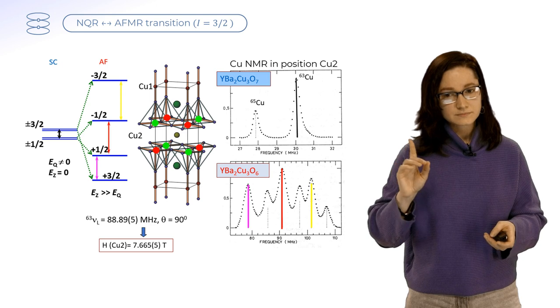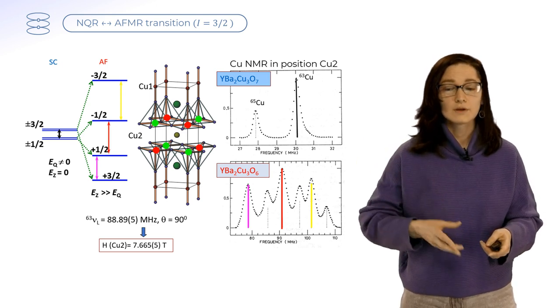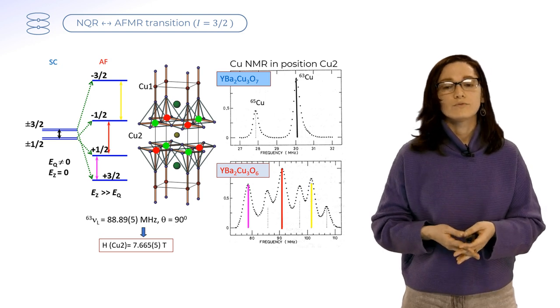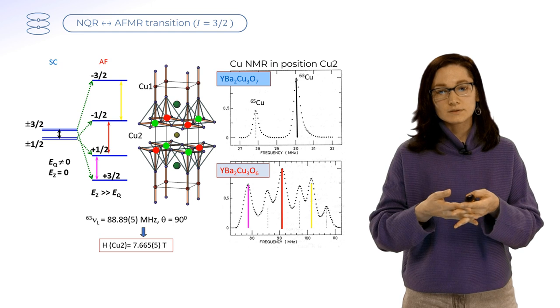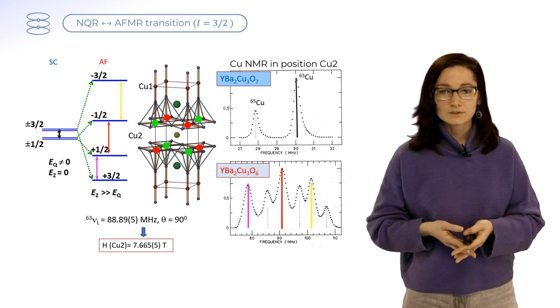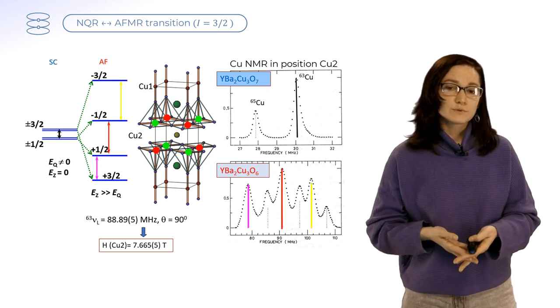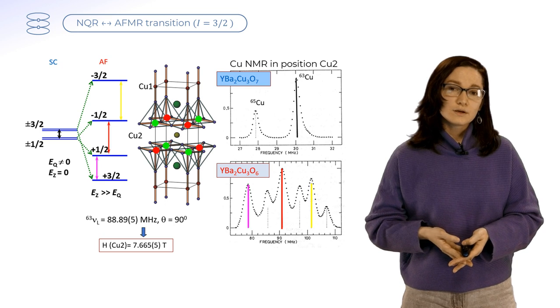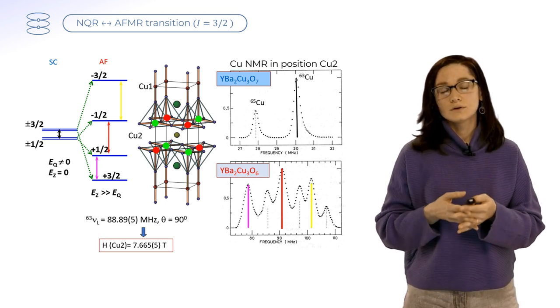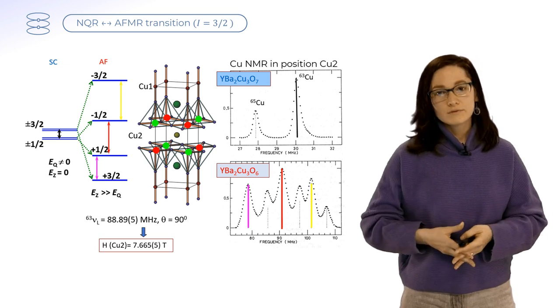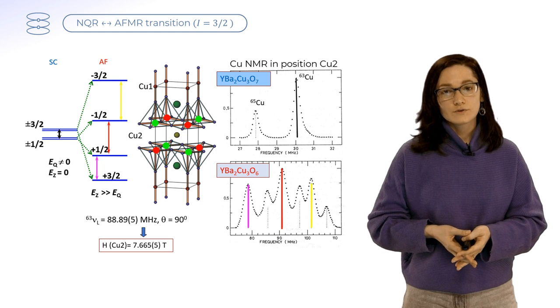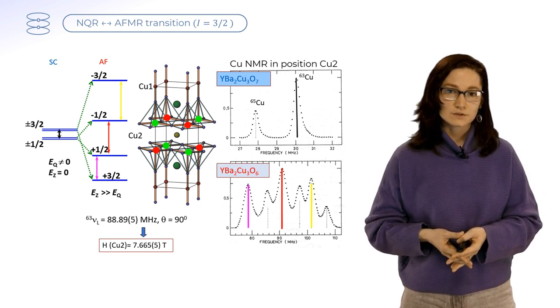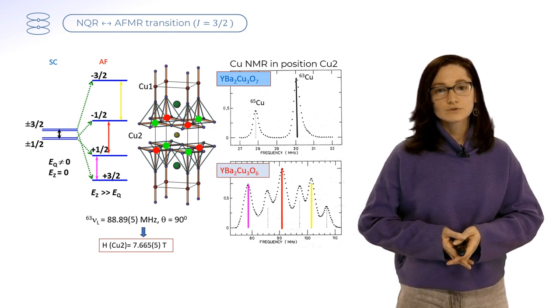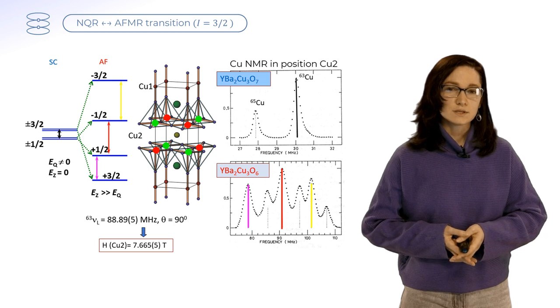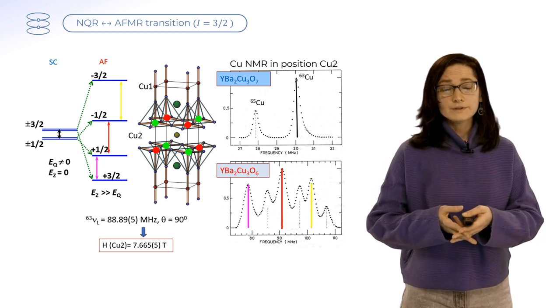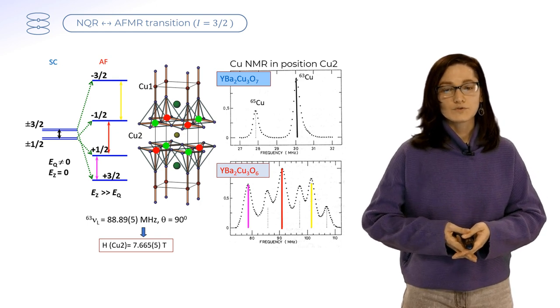Note that the other line here on top stands for the other isotope of copper. And the field on the nuclei of copper for this line is significantly smaller. The line is located at 30 megahertz. So, using NMR spectroscopy, we defined the fields on the nuclei on the copper 2 position, and we even studied the magnetic structure of the antiferromagnet compound. It is G-type magnetic structure. The magnetic field at the copper 2 position is about 7.6 tesla, and all these studies were later confirmed by neutron experiment.